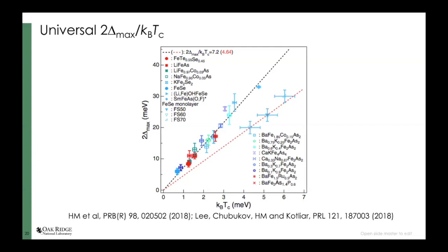There are exceptions, which is the monolayer iron selenium that is shown in here, the red line. For these materials, you can always argue the TC is not accurate, it's purely 2-dimensional, and there is evidence made by ZX Shen that there is a very strong electron-phonon coupling. So it's reasonable to expect for monolayer iron selenium, you have some deviation from other bulk materials.